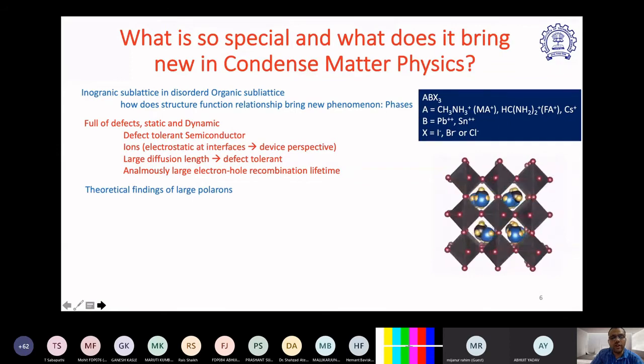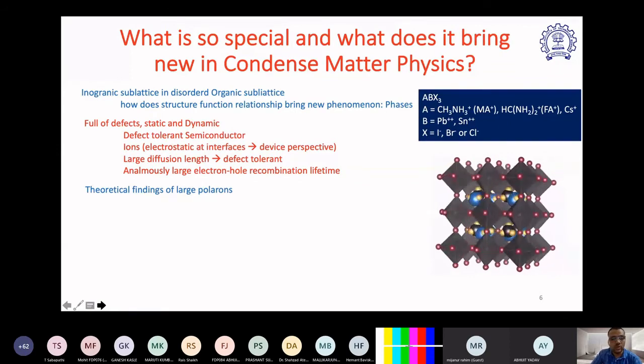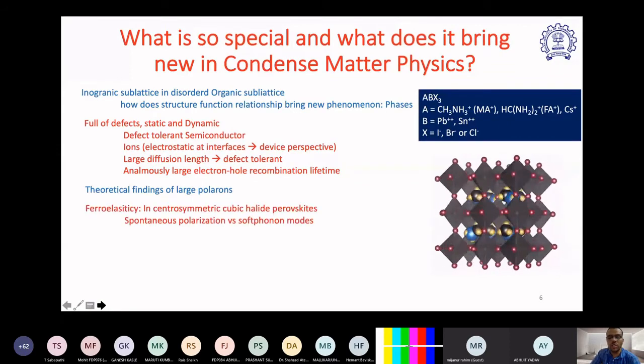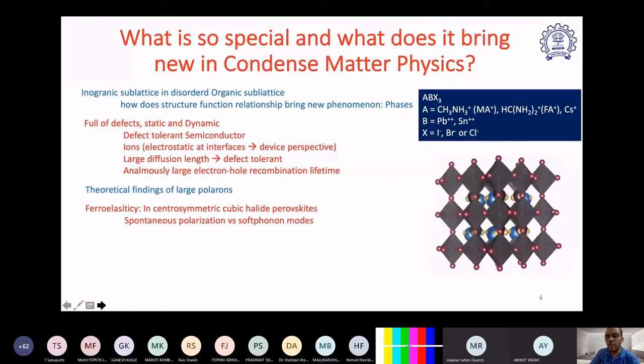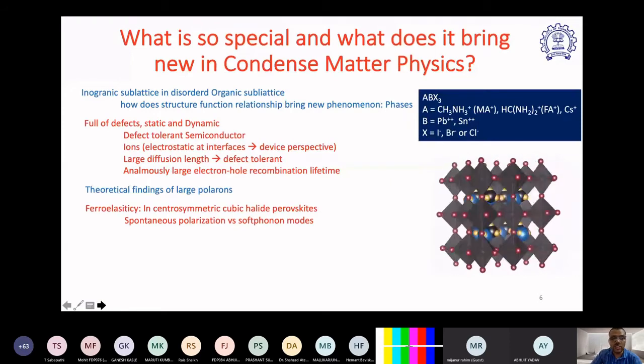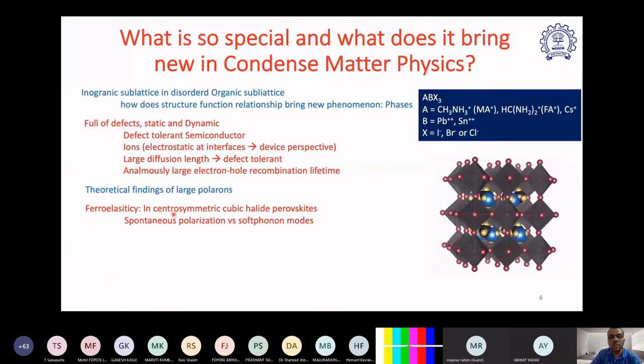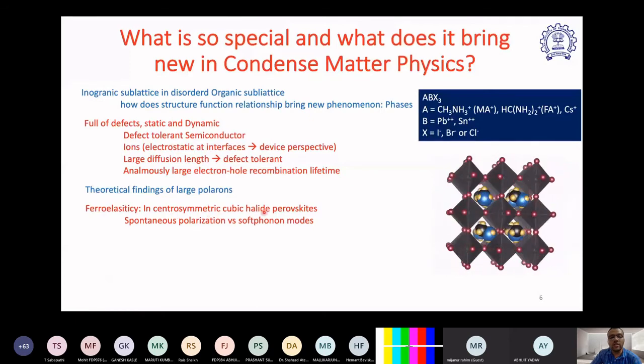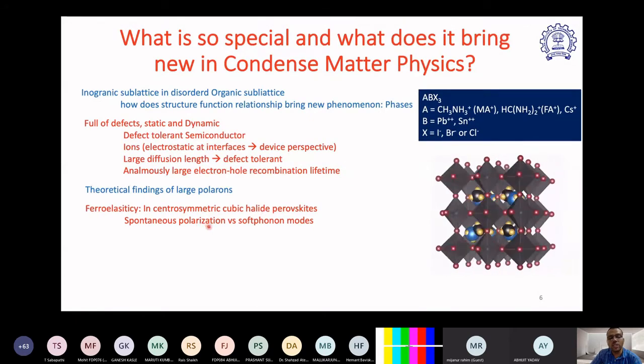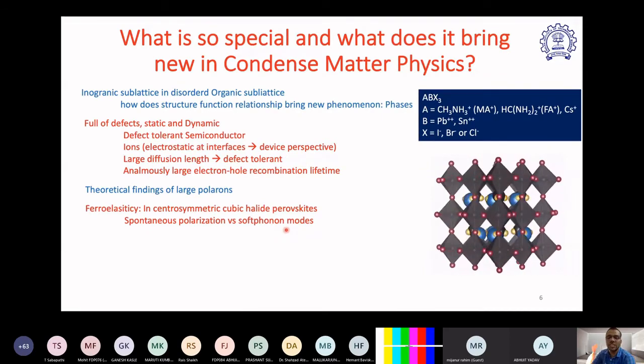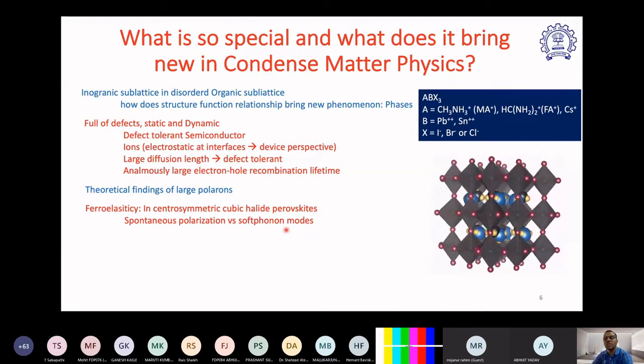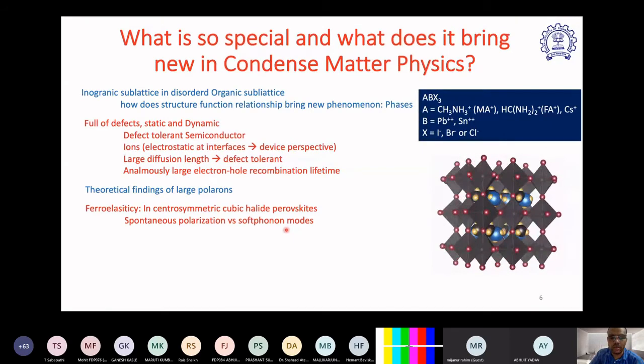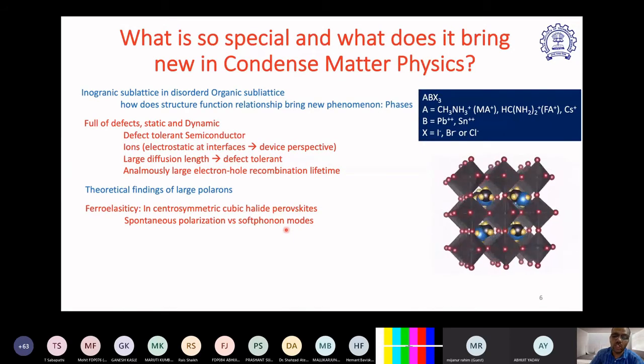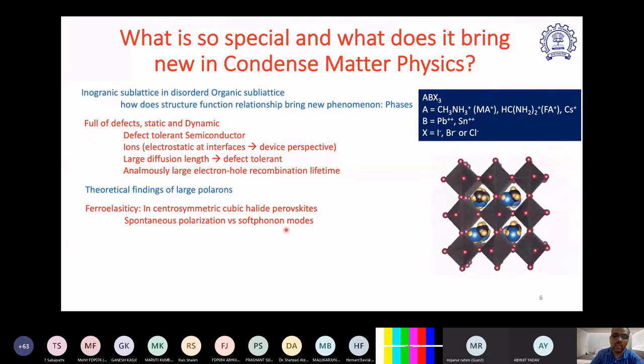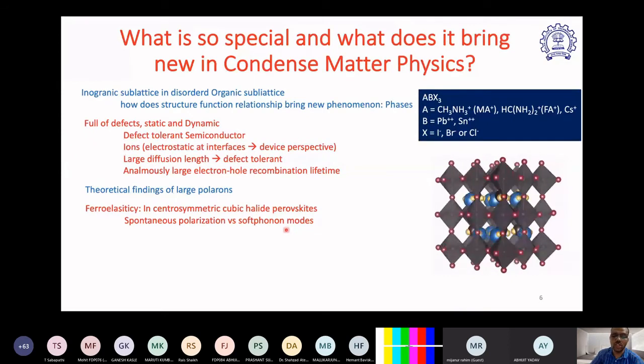There are theoretical findings of large polarons. What are polarons? Polarons are basically charge carriers coupled with the lattice. Ferroelasticity in centrosymmetric cubic halide perovskite: spontaneous polarization versus soft phonon modes. Generally, ferroelasticity is observed when the crystal structure is non-centrosymmetric. In the cubic structures of some halide perovskites, we still see spontaneous polarization.